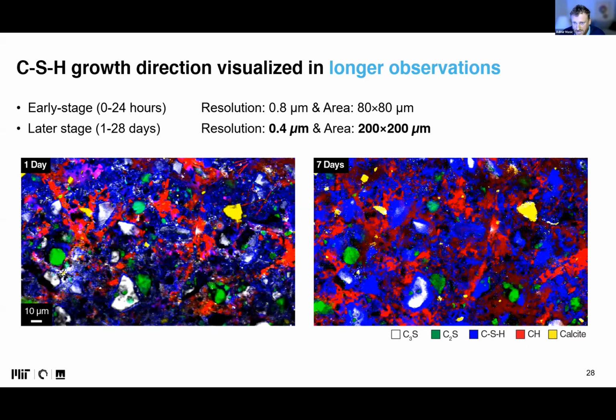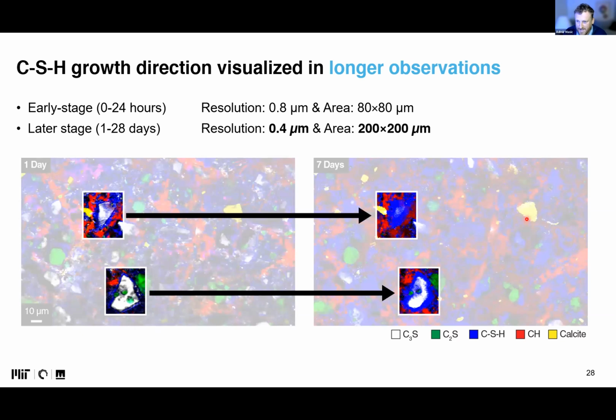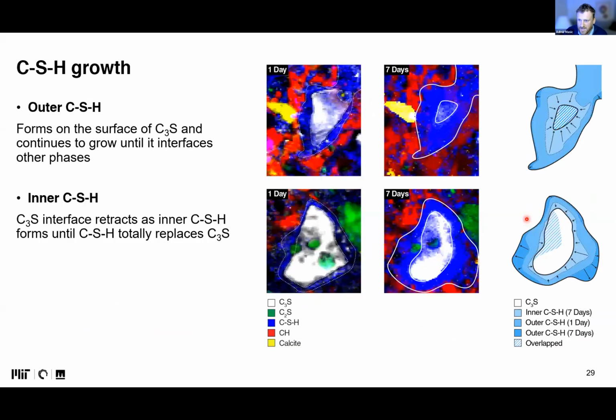I introduced this slide simply because I wanted to show that there is calcite. We can put some calcium carbonate inert material there and have some references, but also in perspective, we'll see this can be easily studied. Here we can see that after 7 days, alite is basically consumed in one grain, but still present in another grain, and there are different parts of CSH that are formed. One that goes inside the grain, another that grows on top of the grain, and so you can do all these kinds of investigations.